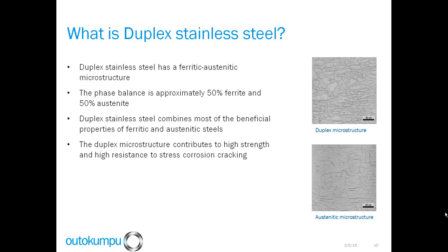When we look at the duplex stainless steel, it's comprised of approximately 50% austenite and 50% ferrite, as shown in the micrograph. Duplex stainless steels combine the beneficial properties of both austenitic and ferritic stainless steels, and this includes the high strength as well as high resistance to stress corrosion cracking.